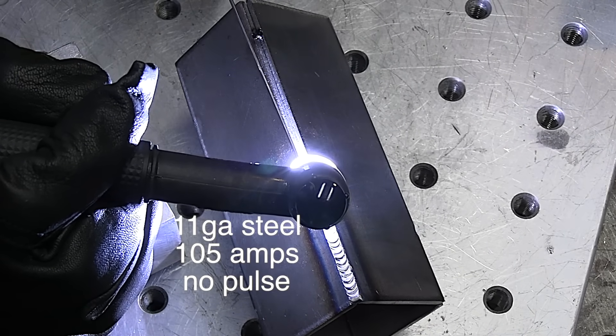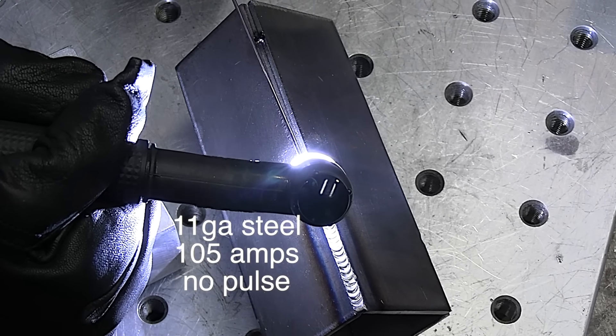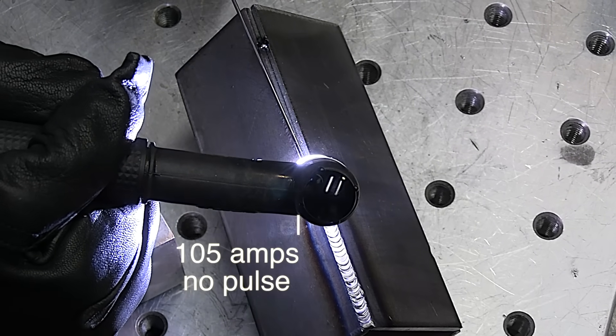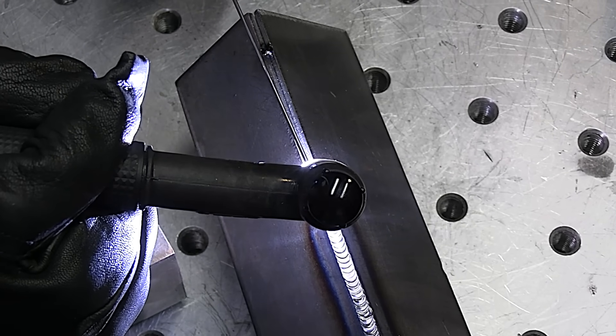First up, 11 gauge cold rolled steel. I'm using 105 amps. I am full pedal for this. No pulse, just straight current.